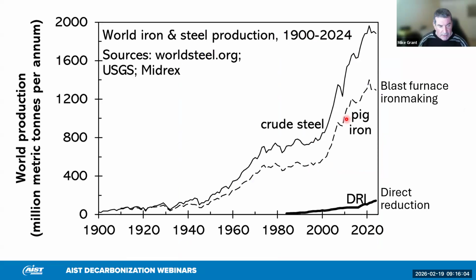So first of all, let's look at the growth of steel production in the world. Up until about 2000, the world produced less than 1 billion tons, around 800 million. And most of that was made with the classical blast furnace, basic oxygen furnace processes. In about 1980, a new process was developed, direct reduced iron, primarily a natural gas-based process. And this started to grow because it provided an alternative for steel making in countries where natural gas is relatively inexpensive. But starting around 2000, we saw exponential growth in steel making, primarily still, even though these are the two most emitting processes in steel making. The growth was primarily in the blast furnace BOF process.